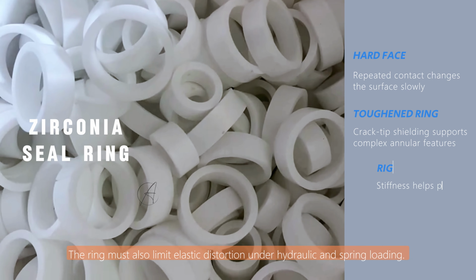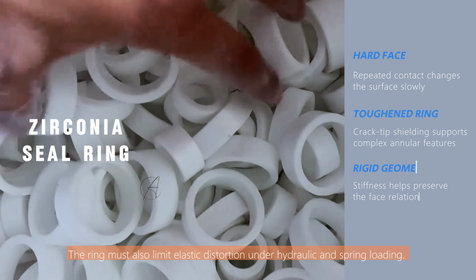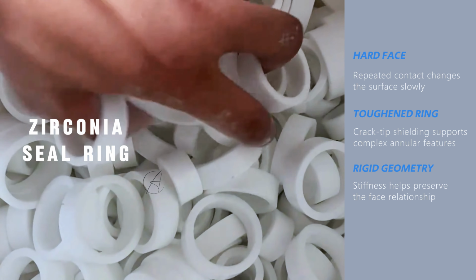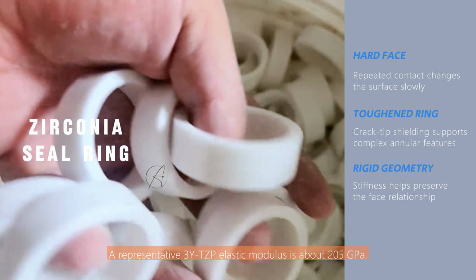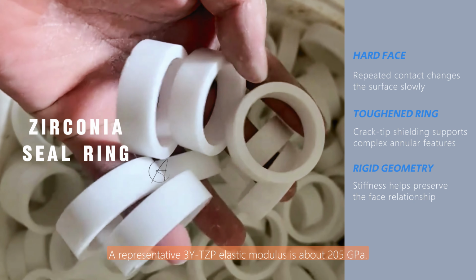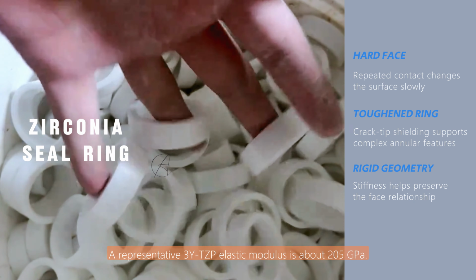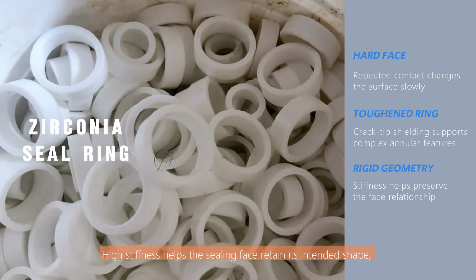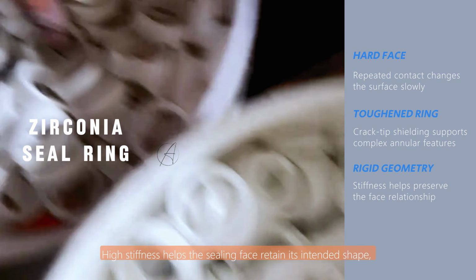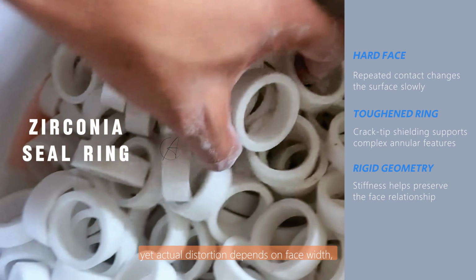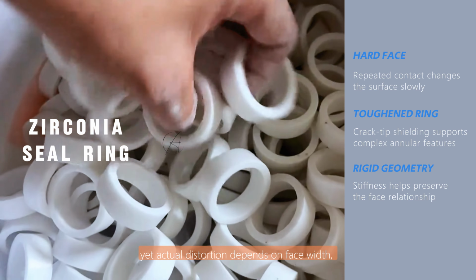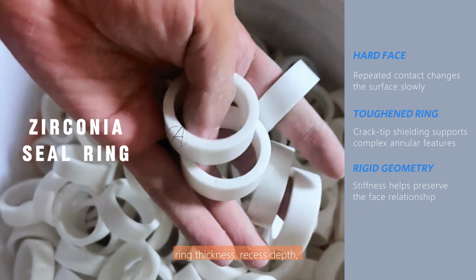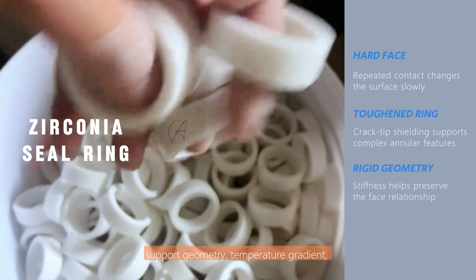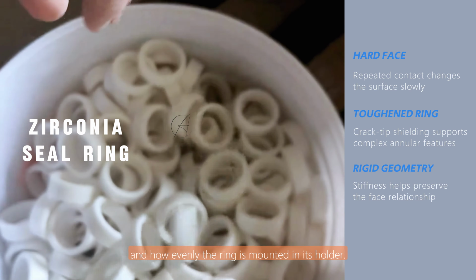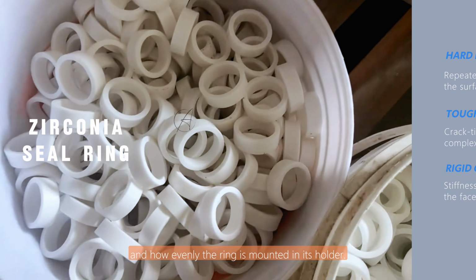The ring must also limit elastic distortion under hydraulic and spring loading. A representative 3 Y-TZP elastic modulus is about 205 gigapascals. High stiffness helps the sealing face retain its intended shape, yet actual distortion depends on face width, ring thickness, recess depth, support geometry, temperature gradient, and how evenly the ring is mounted in its holder.